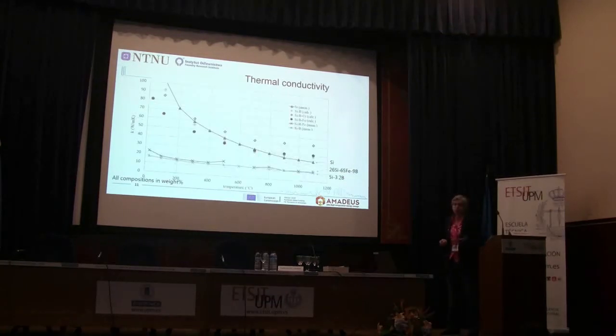We have also started to measure the thermal conductivity again, because I see a lot of modeled data, and since I'm an experimentalist, I would like to have proof that the modeled values are the right values. If we look at silicon, the measured and the modeled values are in the same area. If we are calculating for the chromium, iron, boron alloy, we see they should be a bit higher. However, we have started to measure this.